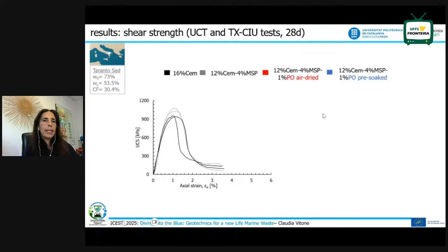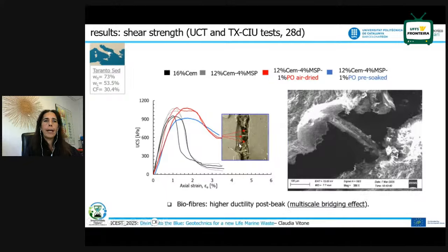So now let's have a look at some of the results. These are results of unconfined compression strength. In black are the control mixtures with 16% of cement, and in gray the mixture where the cement has been replaced by the shell powder. Again, you can see here with the Taranto sediment that we have a similar behavior. If we add the fibers, we obtain a mixture with similar strength, in particular with air-dried fibers, but higher ductility post-peak. This is likely due to the bridging effect that you can see here, the fibers essentially acting as bridges at multiple scales, both at the scale of the element volume at the laboratory, at the scale of the centimeter that we can see with the naked eye, and at the scale of the microscope.